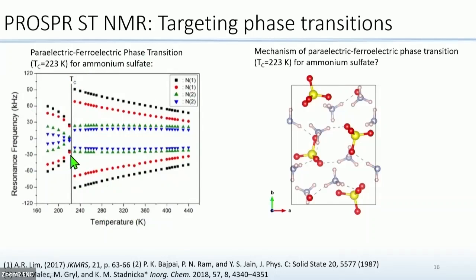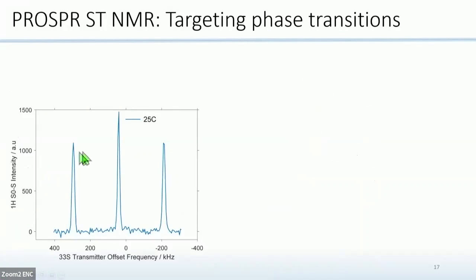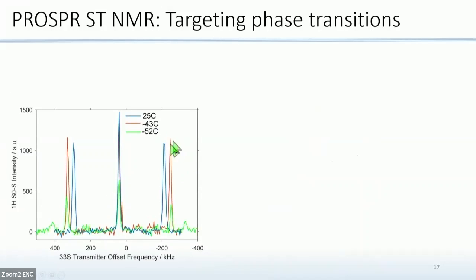Then we were wondering if we could get a similar measurement for sulfur in NMR, because it hasn't been done so far. So we also grew a single crystal, and we managed to measure it pretty rapidly. This is the sulfur measurement, and then we gradually reduced the temperature. We saw here that the satellites are much more sensitive to the change, while for the central transition the change is too small to observe. Then at minus 52 degrees, we saw something interesting. The peaks here look like they still belong to the paraelectric phase, but here it looks like there's some kind of new phase. We think this happened because there was some kind of temperature gradient in our sample.